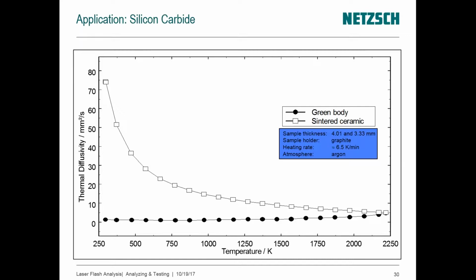And then as we cool down back to room temperature, we keep measuring again. So that's what you see represented here with the squares. You can see the big difference between the green body and the sintered and fired silicon carbide. That's the silicon carbide after firing, after sintering, after burning out, and you see the significant increase in terms of diffusivity. Again, that is expected. But in this measurement, we are able to document that to you. In one run, we measure going up and we measure going down, and you see the difference.